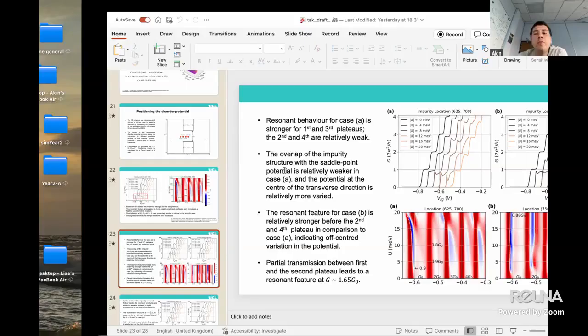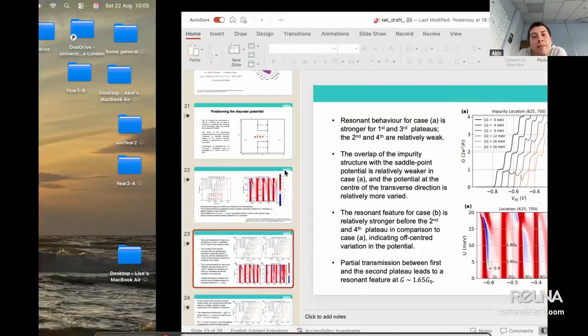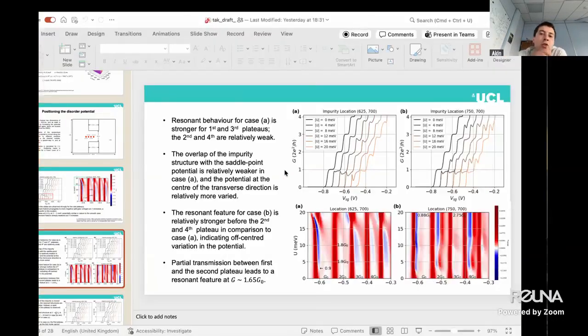We move the impurity further into the structure, and from outside to inside, we see changes in the effects. And what is interesting to see is that the resonant behavior in odd or even plateaus differs in this case. So as we get closer into the saddle point, the impurity starts overlapping with the potential in the environment, and that will create different effects. So in the case A, this is much weaker. We see the center.